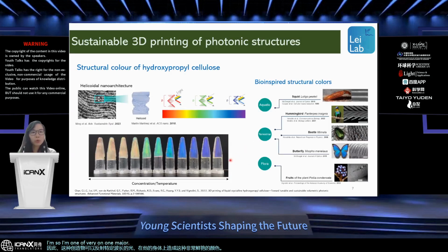One major challenge in converting these materials into 3D printing materials is that we need to solidify the materials and at the same time maintain the helicoidal nanoarchitectures. In order to have this kind of structural color, we need to dissolve a high concentration of polymer in a solution. When we use some cross-linking method to solidify the materials, most of the time the helicoidal nanoarchitectures will be destroyed. Therefore, the color of the materials will disappear.